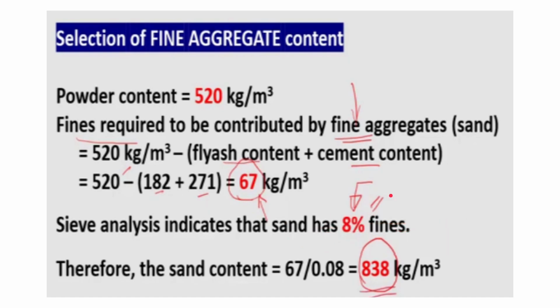So as I told you, if we take 100 kg, we'll get only 8 kg sand which is passing through the 0.125 mm sieve. Therefore, for 67 kg of sand passing through 0.125 mm, we have to take sand content as 67 divided by 0.08. So it will come around 838 kg per meter cube. So if we take 0.08 of 838 plus 182 plus 271, we will get the powder content of 520 kg.